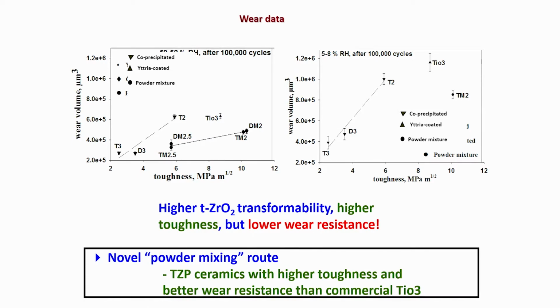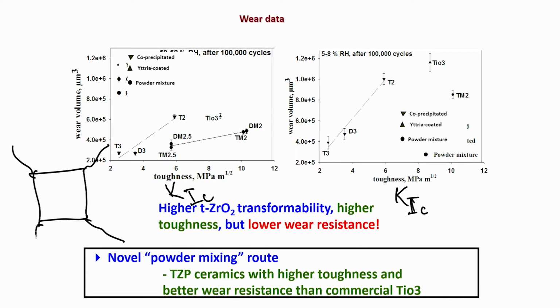Now, one of the intriguing results is that when you measure that wear volume and plot it against fracture toughness, K1C, which is measured using the indentation cracking method here. Indentation cracking means you take a Vickers indent. In ceramics, a Vickers indent causes cracking. Then you measure the total crack length 2C and the indent diagonal 2A, and from these measurements you can find the fracture toughness K1C values.